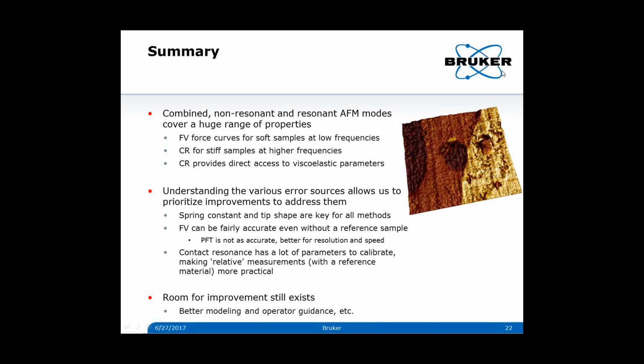The next one says, how does frequency of approximately 2 kilohertz in PFQNM affect the measured modulus values? So it depends on the material. Definitely, many polymers have a lot of variation with frequency, and you can even see that if you just do measurements in PFQNM and you compare them to force volume, you'll see variation. It could be a factor of 2 or a factor of 3 in modulus. But that's a real change. The storage and loss modulus are functions of frequency, and that's the reality of it, and that's kind of interesting too.